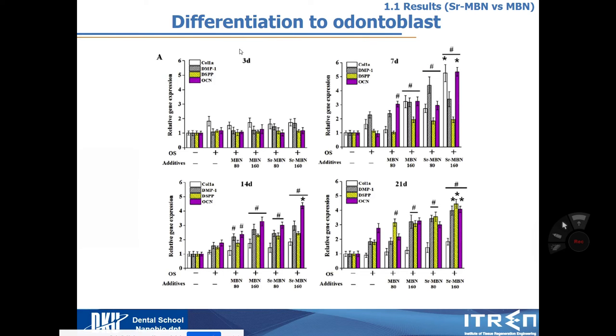And then I can check the differentiation potential to odontoblasts from human dental pulp stem cells. Over time, at 3, 7, 14, and 21 days, I can observe an increase in odontoblast differentiation gene expression, including collagen 1A, DMP1, DSPP, and OCN. Compared to MBN, strontium MBN shows a little bit more increase. And when you compare strontium MBN 80 and 160, you can also detect that 160 is better than 80. So at 7, 14, and 21 days, gene expression generally increases.